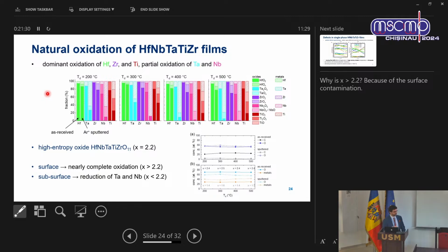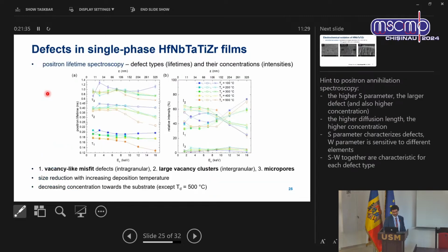Also, the defect structures just confirmed our picture. We observed 3 types of defects besides the vacancies and some clusters which were present mainly in the case of the amorphous films. We observed some micropores, but with really low concentrations, really low intensities. And also we have seen that we are obviously improving the crystallinity of those films. We are reducing the average size of the defects. Also, we are reducing their concentration with increasing deposition temperature. So that means that the film at 500 degrees is a really good initial state for further studies.